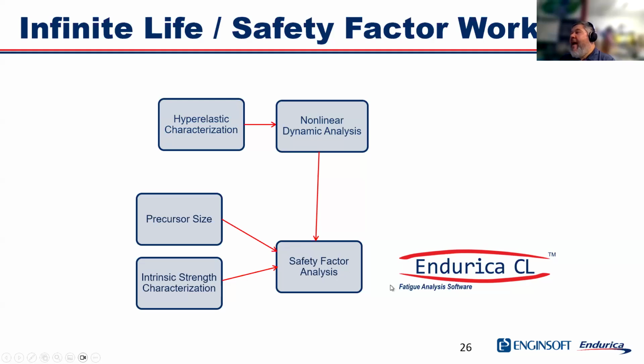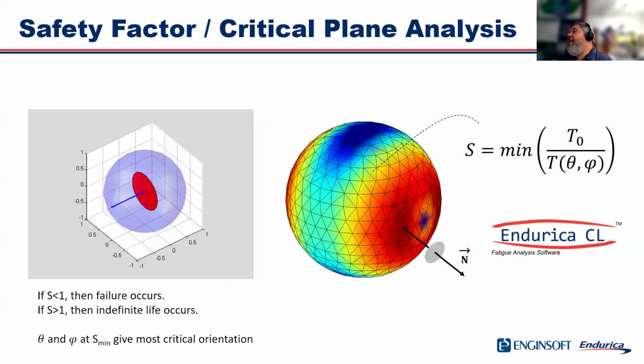The safety factor is an output that you can request from the Endurica CL fatigue solver. So you just put in your strain history, put in your material properties, and one thing you can get out is safety factor. When you use the safety factor analysis in Endurica, in cases where you have multi-axial loading, it is going to use a procedure called critical plane analysis. And the purpose of critical plane analysis, like I say, is to take account of the multi-axiality of loading.